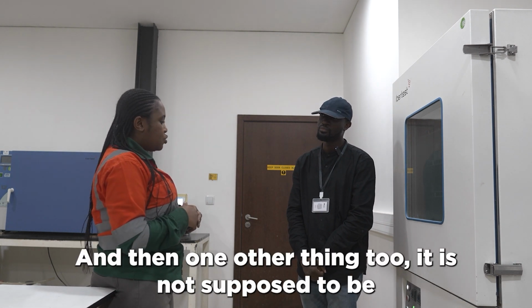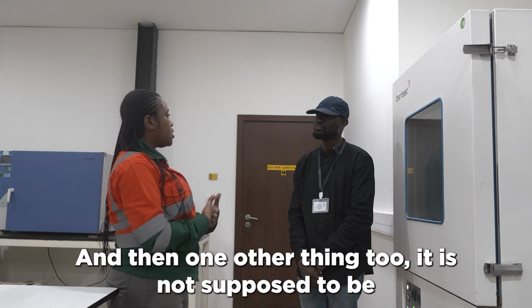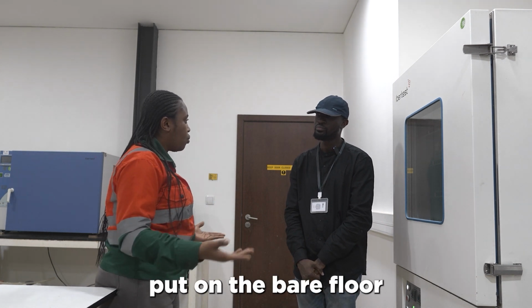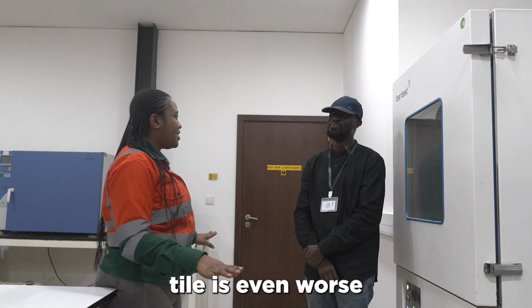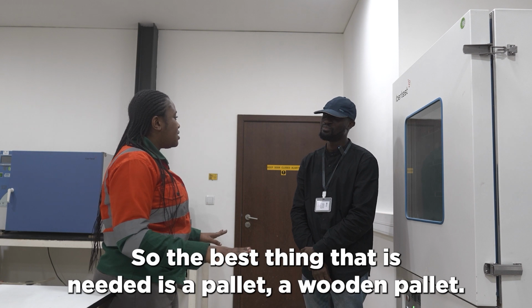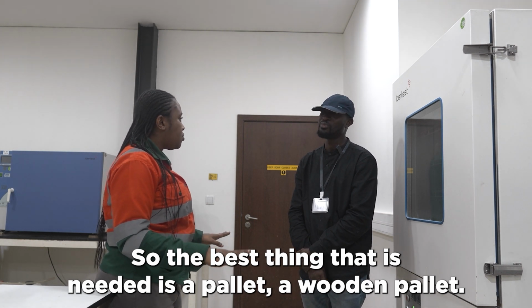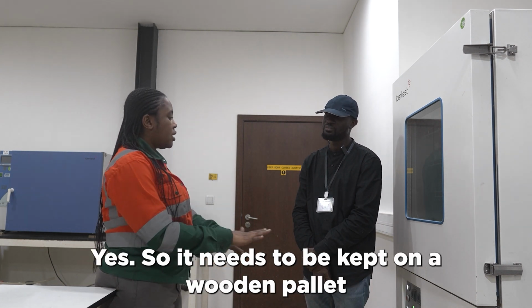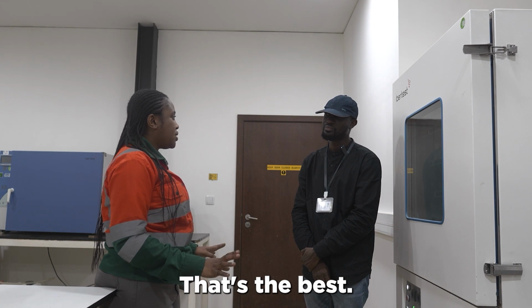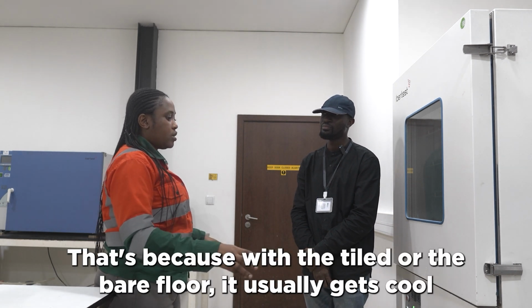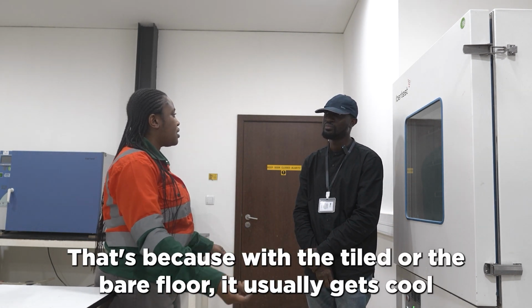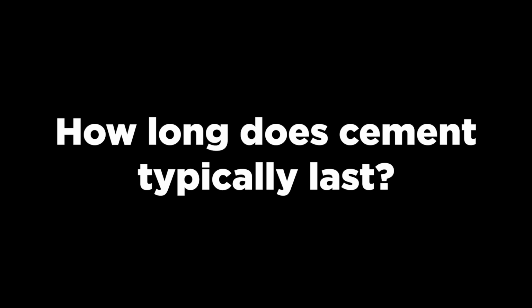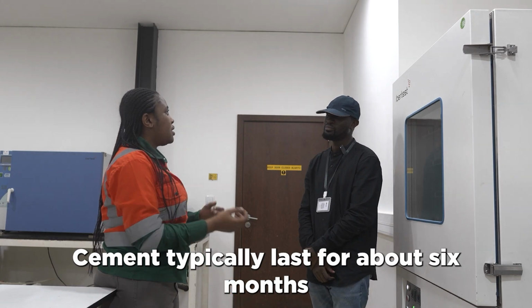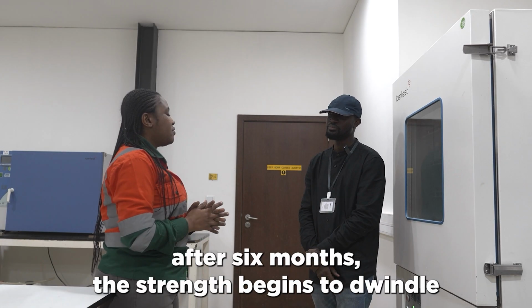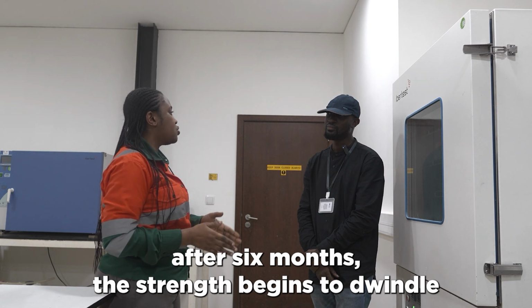One other thing is it's not supposed to be put on the bare floor. Tile is even worse. The best thing needed is a wooden pallet. So it needs to be kept on a wooden pallet. That's the best, because with tiled or bare floor, it usually gets cool. But how long does cement typically last? Cement typically lasts for about 6 months. After 6 months, the strength begins to dwindle.